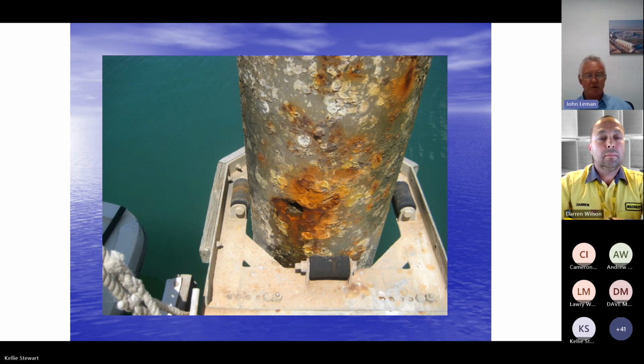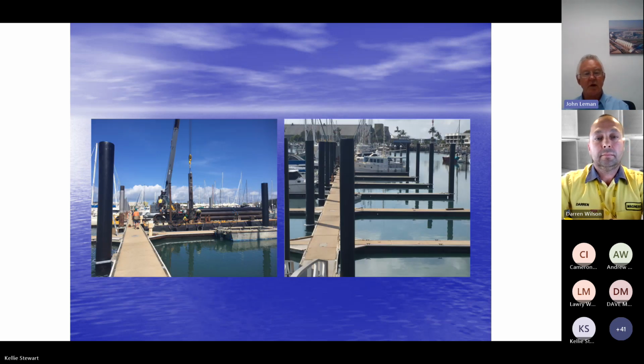What we did with that one, we did some HDPE sleeving in another steel pile on the inside, because it was economics that drove that. But on the right-hand side, you can probably see in the distance some piles with white pile caps on them. They're actually concrete piles. So the solution there was to put an FRP fiberglass pile sleeve on the outside of it, and that worked really well. We did those about 5 or 6 years ago, and it was a good outcome.